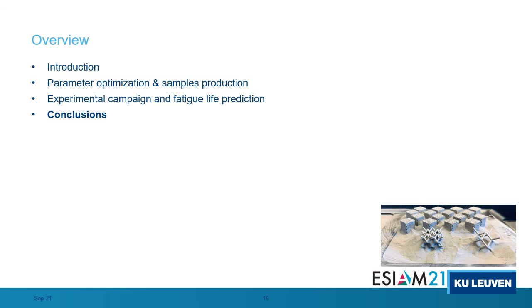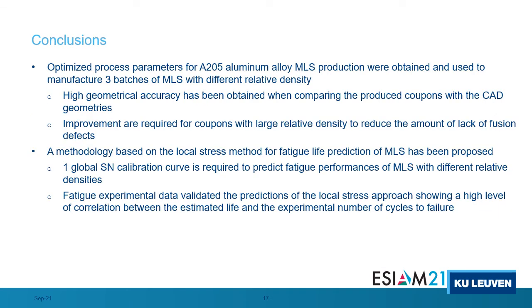To conclude this talk, it is possible to summarize the main findings of this study as follows. A quasi-optimal parameter set for production of metal lattice structures with the A205 was obtained. Although this parameter set ensured high geometrical accuracy, improvements are still required to reduce the amount of internal defects that were generated for the coupons with higher relative densities. A methodology based on the local stress method has been proposed to predict the fatigue performances of the metal lattice structures. The procedure consists of one single set of SN data that is then converted into a local SN curve. This local SN curve has been successfully used to predict fatigue performances of the metal lattice structures investigated in the study. In fact, the comparison between the predictions and the experiments showed high correlation, highlighting the prediction capabilities of the local stress approach.